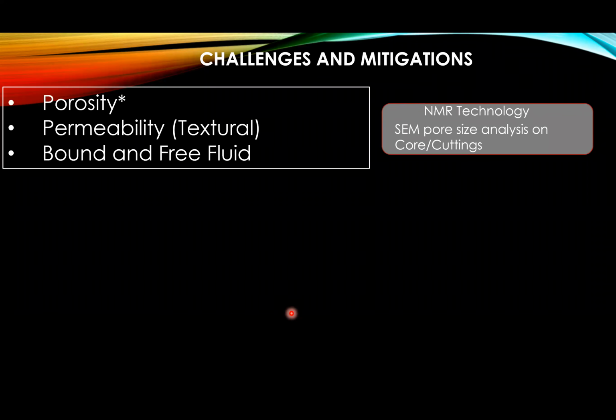But it can provide you with grain size variation. NMR T1 and T2 measurements are actually based on grain size variations and fluid type variations. Particularly from the T2, you can derive pore size variations with time. Generally for the smaller pores, the NMR signal will come earlier in time, and the larger pores will have the signals coming at a later time.